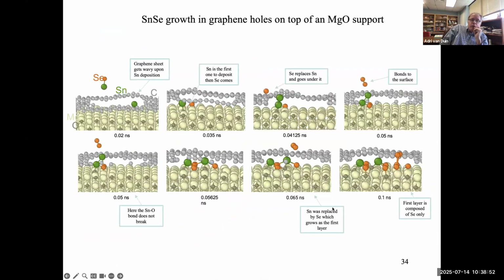Now, where graphite comes into play, it turns out that you can actually grow these things also very well on magnesium oxide, but in particular, if you add a defective graphitic material on top, a kind of graphite mask, you can really control the growth much better. Here the dark gray area is essentially graphene with a big defect.